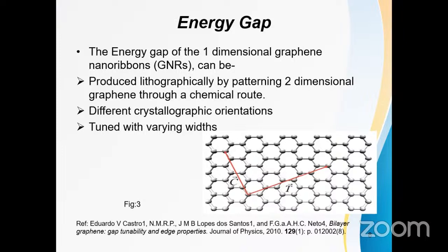Earlier theoretical work showed that this energy gap depends on the width and crystallographic orientation of the graphene nanoribbons, similar to carbon nanotubes. The first experimental work on GNRs has shown that a transport gap can indeed be opened up by patterning graphene into nanometer size ribbons or constrictions.